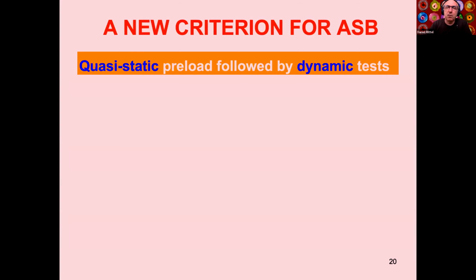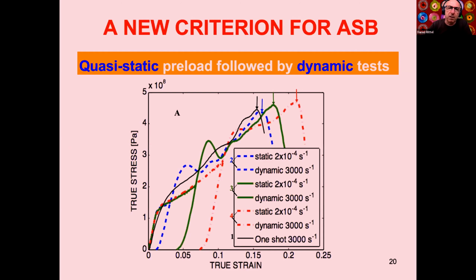So let's look at some experiments we performed in order to understand better the phenomenon of shear localization. So what we did was to take a specimen, and we knew the static failure strain. So what we could do was to quasi-statically load or preload the specimen, unload it, and then impact it, and record the static and dynamic curves. So that looks a little bit dense, but look, for instance, at those stress strain curves. Look at the black curve. That's a monotonic dynamic test. This is the failure strain. Let's look now at the green one. We load statically here. I hope you can see my mouse. We unload, let it cool, and then we reload dynamically, and then the total strain is, of course, larger, and so on and so forth.